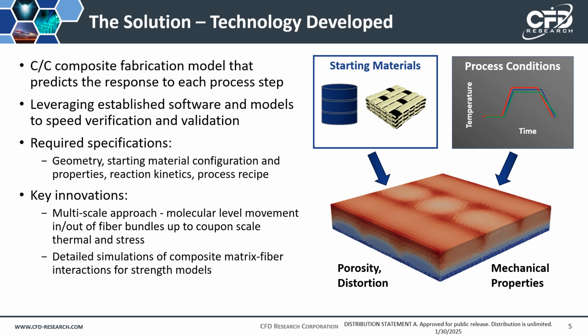By modeling the process at the scale of a unit cell with the fibercloth geometry, we can predict where pores and cracks are most likely to form within a typical unit cell, in addition to large-scale effects such as imperfect distribution of the resin, incomplete pyrolysis, or excessive stresses and distortions in different sections of the final part. Another unique and innovative aspect of this effort is that we are linking the process model with other capabilities CFD Research has developed for detailed simulations of how the composite component performs in flight, or how to plan flight trajectories to safely use available materials.